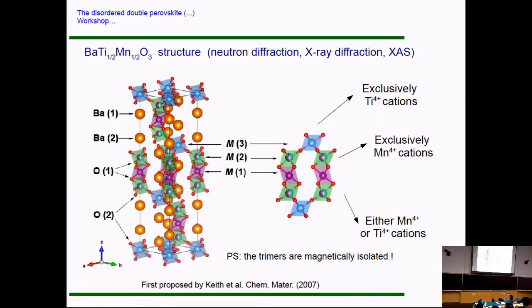So our proposal for the structure, which is actually not really ours, was thought of before. We were just verifying that with different techniques. But the current understanding about the structure is that the M3 site is exclusively occupied by titanium cations. The M1 site, sorry, by this arrow, the M1 site is here, and this is occupied exclusively by manganese 4+ cations. And you have the M2 site, which has mixed occupants.